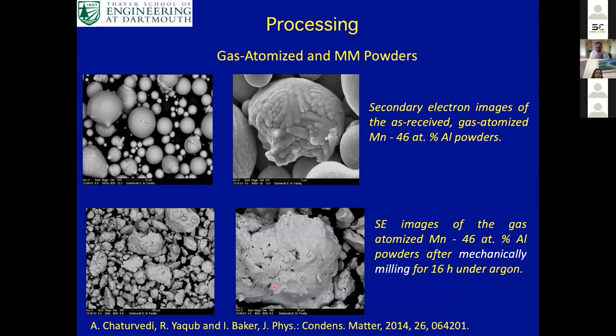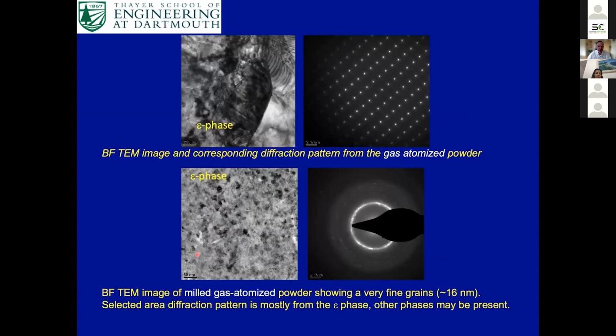So turning to the processing, I'm going to give you a little bit of work we've done on the process and then compare it to what other people have found. So we made the manganese aluminum a variety of different ways. One was by gas atomization. You can see the gas atomized particles that we've got here, which are largely spherical particles. We then also took these and mechanically milled them as well. So this is in the epsilon state, and you can see there's a change in particle shape and size a little bit after mechanical milling.